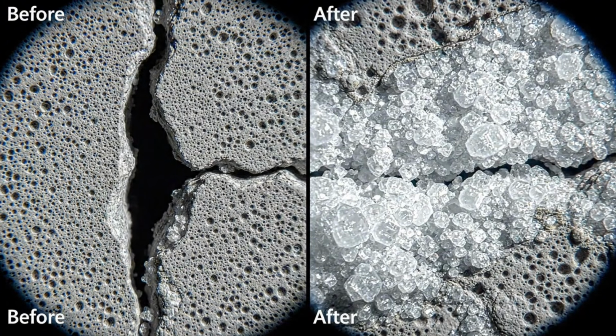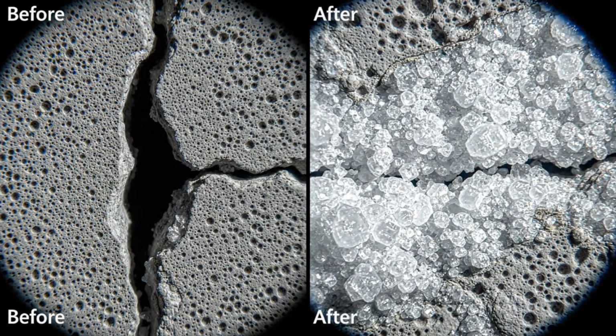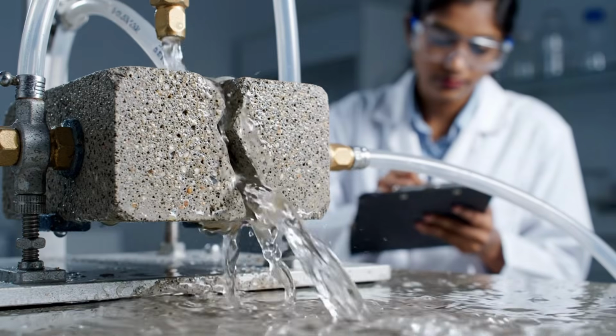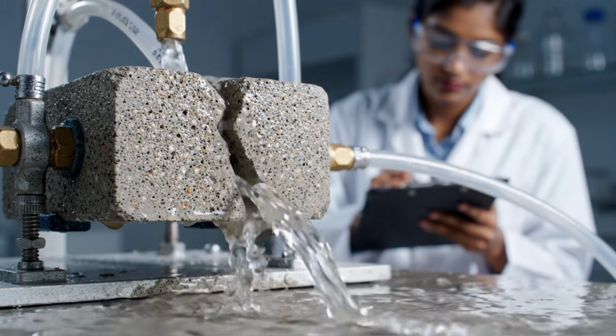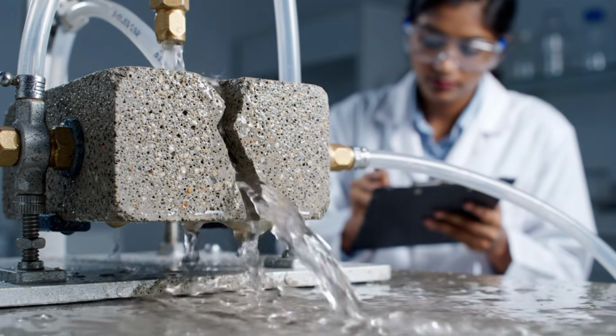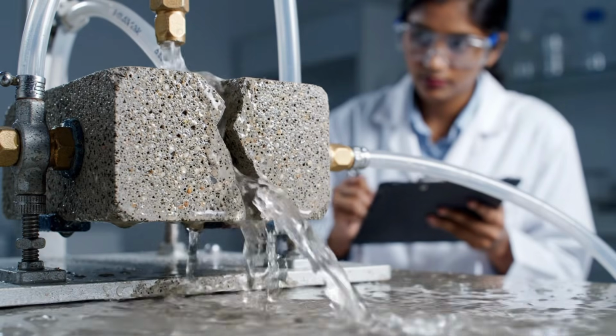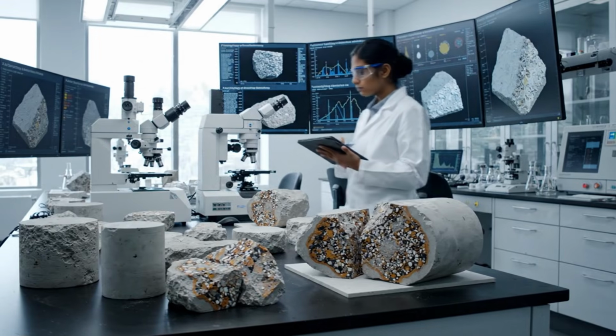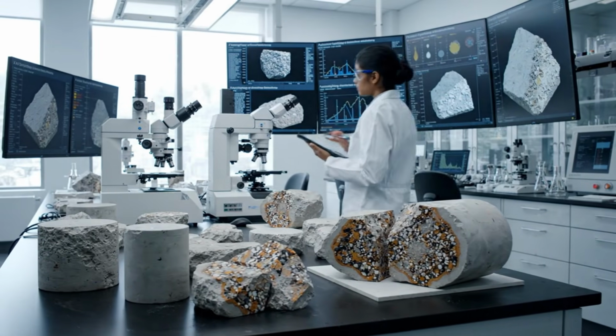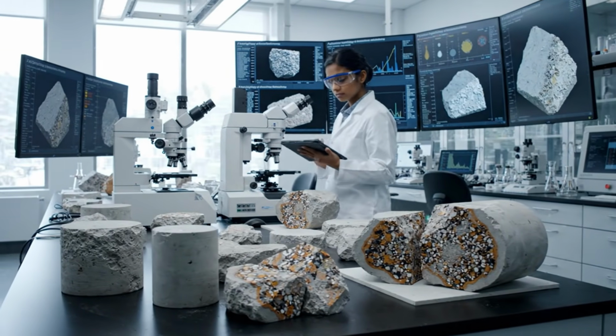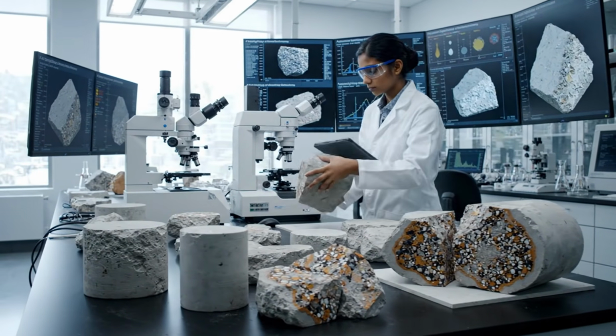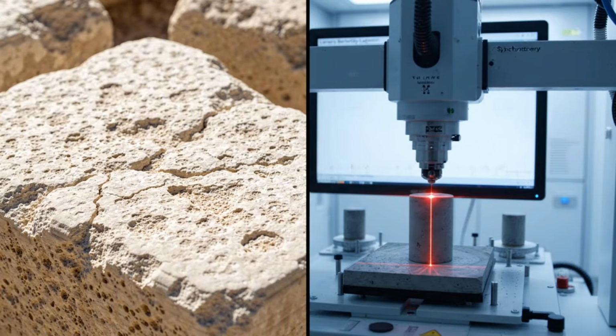The team tested this. They cast hot mixed replicas, cracked them 0.5 millimeter wide, and ran water through under pressure. Within about 2 weeks, the flow stopped. The crack had sealed itself with freshly precipitated calcite. An identical sample made without quicklime never healed. The water just kept flowing indefinitely.